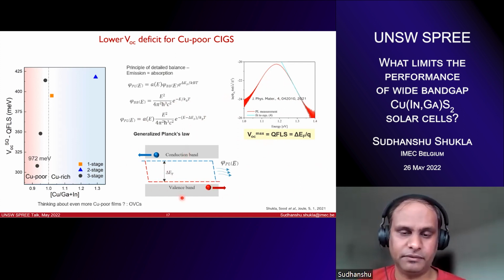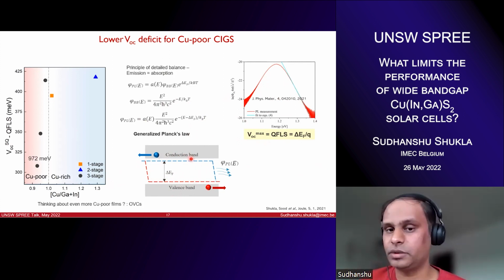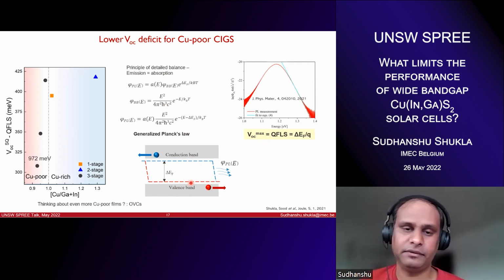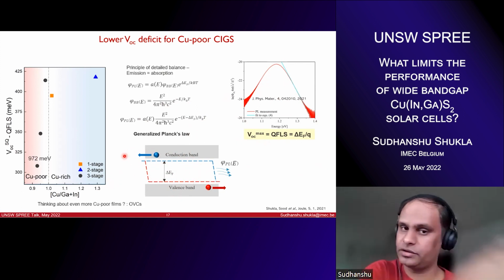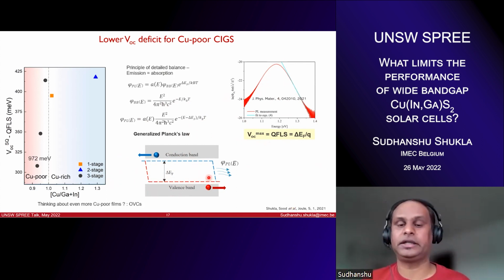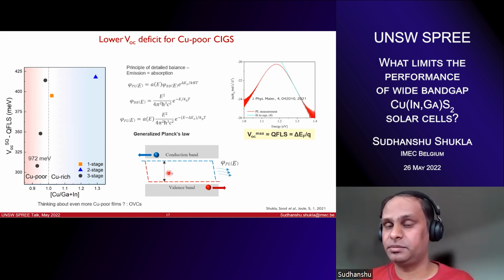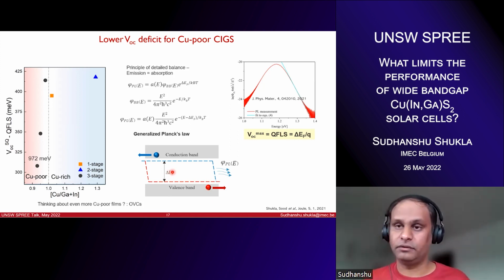But roughly what you see here is you have a conduction band and the valence band, you shine light on it, you split the Fermi levels, so the carrier distribution is not given by one distribution, but it is given by two Fermi levels, quasi-Fermi levels, the electron Fermi level and the hole Fermi level. Electrons go to the electron selective contact and holes go to the hole selective contact, and the maximum VOC that you can get is the delta EF. So this is a metric of the absorbers. It refers to how good your absorber is, because if your internal photovoltage is good, you can extract as much VOC as equal to this internal photovoltage from that absorber. So you want that term to be as high as possible.